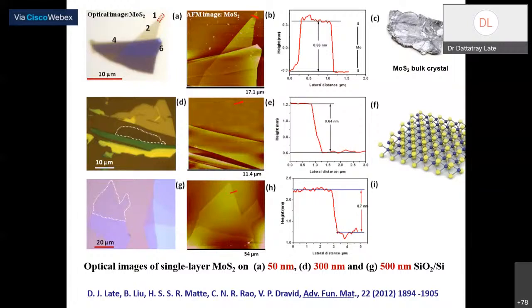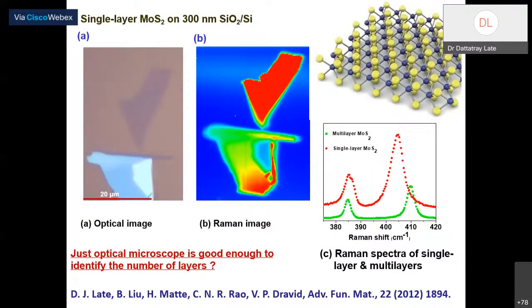Because of the change in SiO2, my optical contrast has been changed. The change in optical contrast gives you different color contrast that I can see under the optical microscope. When I change this thickness of SiO2, I can see the change in the color contrast, and that gives you various color contrasts for the various layers of MoS2. Right? For example, you can see this one layer or multi-layer of MoS2. Of course, we can characterize by AFM and find that these are monolayer in nature and have similar characteristics and properties. But here I have changed the SiO2 substrate, and therefore the color contrast has been changed. Why this color contrast has been changed, I will explain in the next slide.